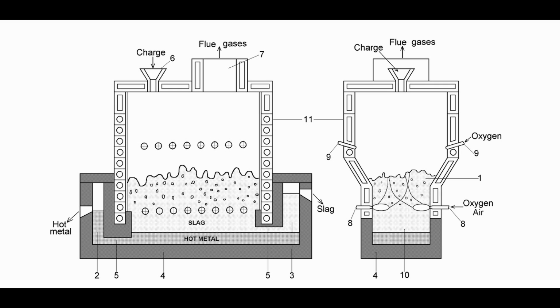After post-combustion, gases flow through the water-cooled gas escape branch pipe at a temperature up to 1700 degrees Celsius into the waste heat boiler. They are burned completely with natural air inflow and cooled to 250–300 degrees Celsius. Gases are transferred to the gas cleaning system and discharged into the atmosphere through the chimney. Flue dust ejection from the unit, measured in the gas escape branch pipe, is on average about 3% of the weight of the charged materials.